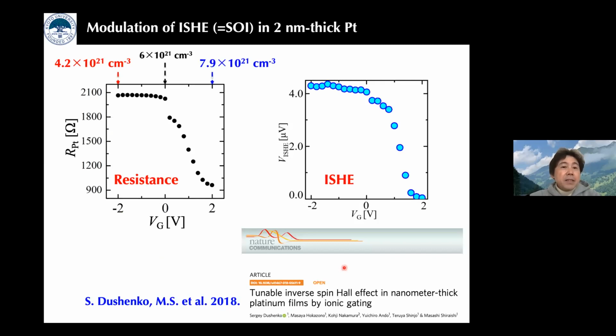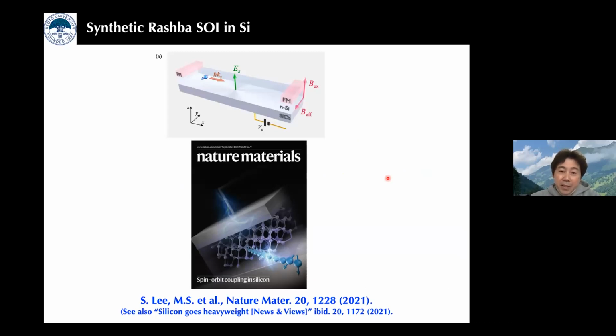So the final example is the ultrathin film. Of course, platinum is a metallic material, but when we fabricate very thin platinum, we can control the resistance of the metallic film by the gate electric field, and more importantly from the spintronics viewpoint, we can largely control the inverse spin Hall effect. Later on, I will explain the achievement in detail. And also in the second part, I will explain the latest results from my group, namely the synthetic Rashba field SOI formation in silicon.